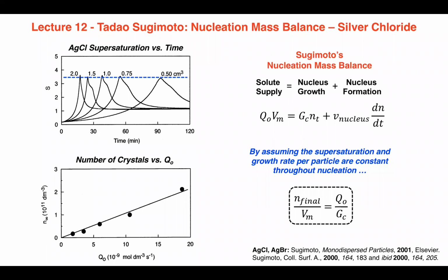They're so good at growing, they suck up solutes with a very small number of crystallites being present. Okay. That is a somewhat counterintuitive result for people, I think, that the number would be related to the growth kinetics. And that growth kinetics being faster would reduce that number is not very intuitive.